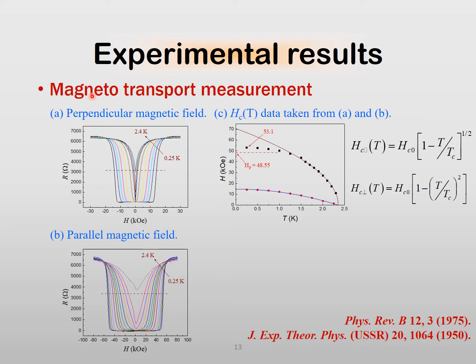When we perform the magnetotransport measurement shown here, the magnetic field was either perpendicular or parallel to the plane of the aluminum nanofilm. We were not able to perform in situ tilted field measurement, so we had to warm the system up, take the sample out, rotate the sample, and cool it down again, which is a bit of a pain. Anyway, when the measured resistance is equal to half of the normal state, we are able to measure the upper critical magnetic field as a function of temperature.